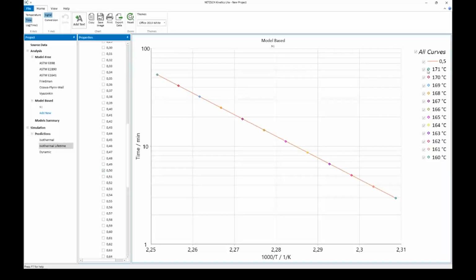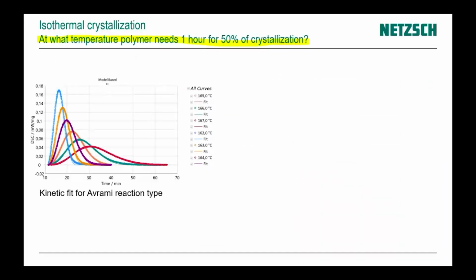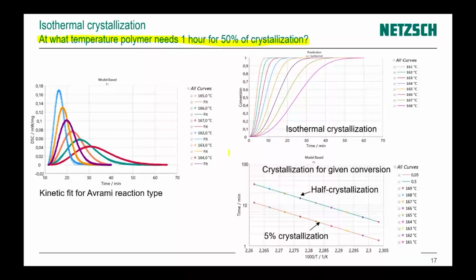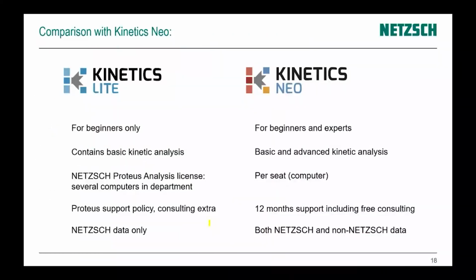The crystallization will be 50% after 1 hour for the temperature 171 degrees. So that is really fast to find these values, and we can make it with Kinetics Lite very fast. Here on the graphic, we have half of crystallization and 5% of crystallization. Here is not a problem.